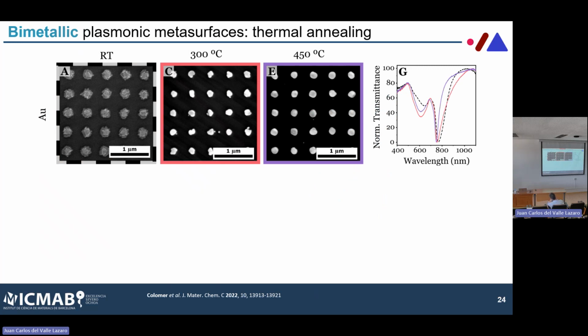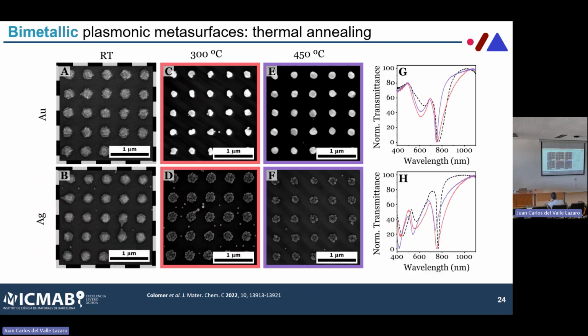The idea was we heat up the system and then we melt the particles together, and these would basically create a single structure. Here you see the case of gold, where you improve the properties, because we indeed create single structures, so we make the resonance a little bit sharper. With silver, we have the problem that silver tends to oxidize, it's a less stable metal, especially when you warm it up. So we ended up creating structures that were actually worse.